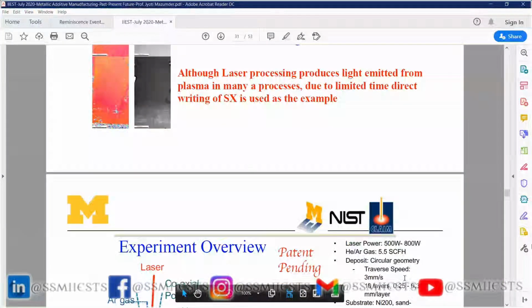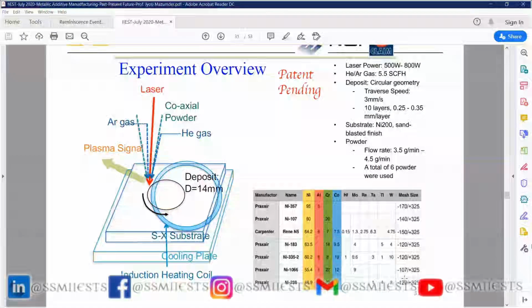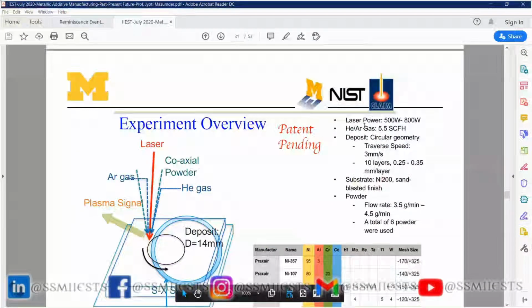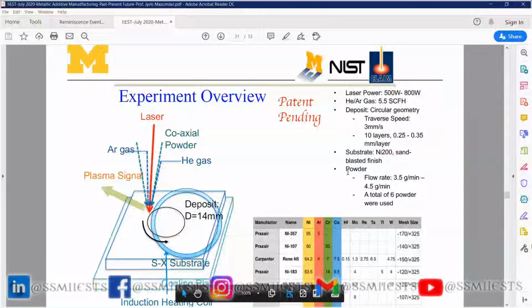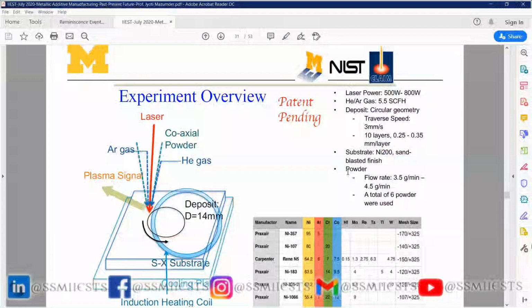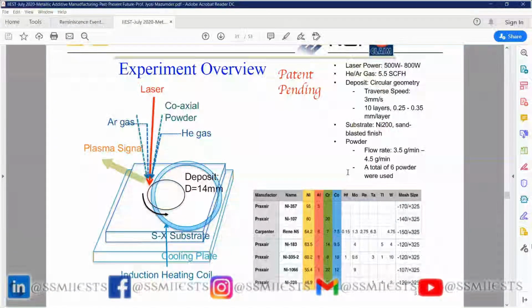Now, how to write a single crystal? I'm talking to the metallurgists, so I assume you know how a single crystal is made. The critical point of making a single crystal is that your temperature gradient at the solid-liquid interface has to be maintained carefully and within a very small, narrow range. That's the challenge. This type of work was funded by the National Institute of Standards and Technology, NIST, in the USA. What we found is that if I combine laser, induction heating, and a cooling plate at the bottom, by controlling it carefully, I can maintain that temperature gradient at the interface.